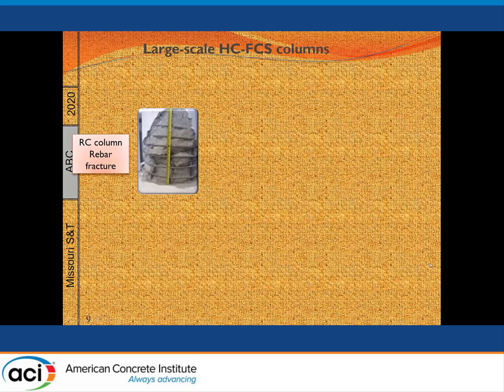And we achieve different modes of failure. This is for the reference reinforced concrete column. This was a well-designed reinforced concrete column. So as you would expect, you get the spalling and some buckling, fracture of the rebar.